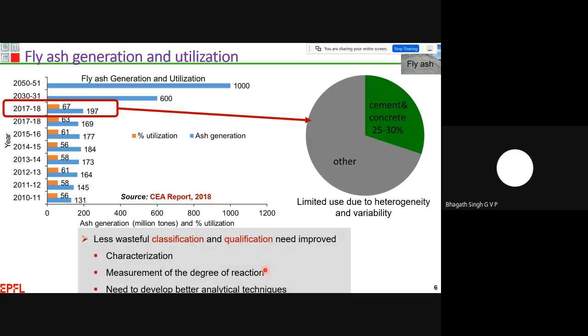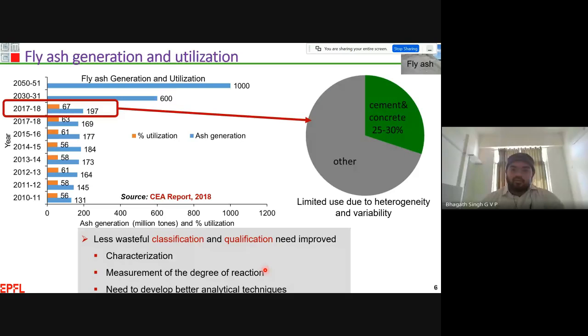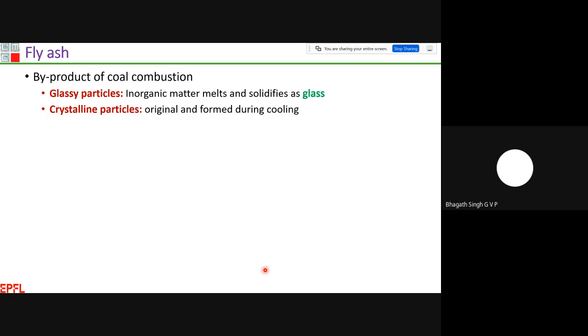On top of this, we have to develop better analytical techniques to quantify the reaction pathways and the quality assessment within a shorter span. The existing methodologies, as per our codes, require a much longer time to determine the reactive silica, reactive alumina and other parameters in the fly ash. We have to develop better analytical techniques to assess the fly ash mechanism. After considering all these factors, I have developed various methodologies in my research.